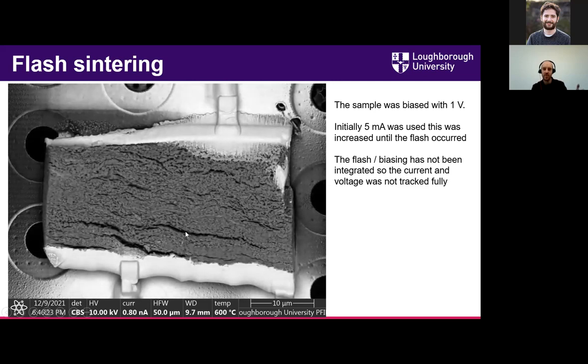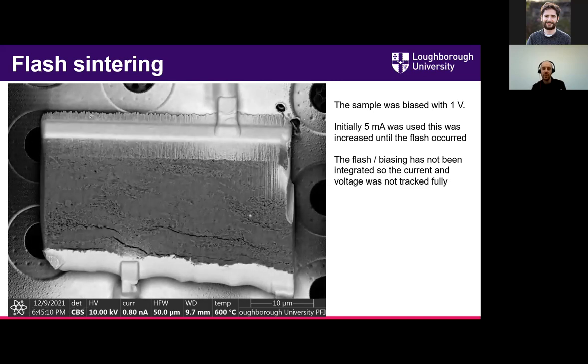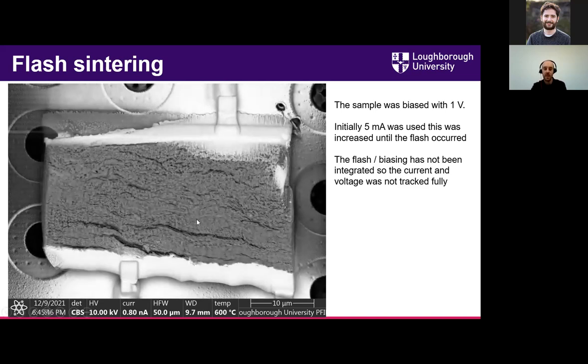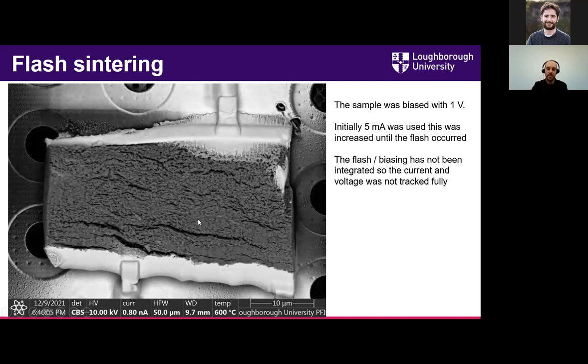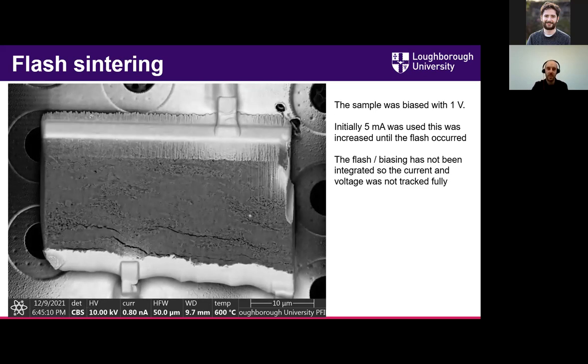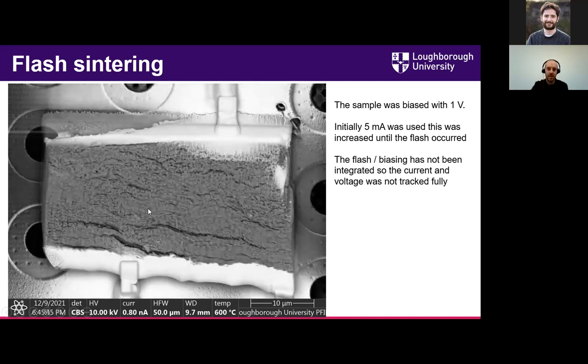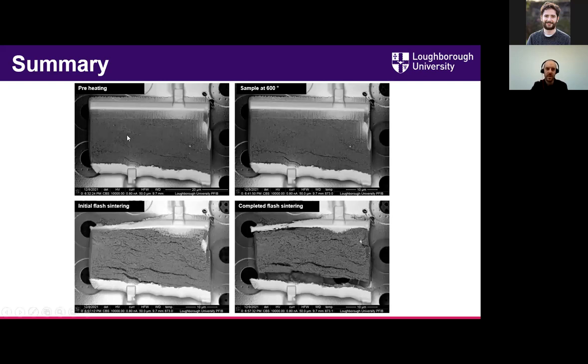and the sample's actually shrunk. And as it's shrinking, it's starting to pull away from the tungsten deposits. This is a sample being flash sintered in situ. So the plan is to be able to observe this as it happens, and we're working towards that. So you can see pre-sintering, sample sintering at 600 degrees, initial flash sintering, and then the completed flash sintering, where the tungsten biasing lines are broken, so we've had to stop the experiment.